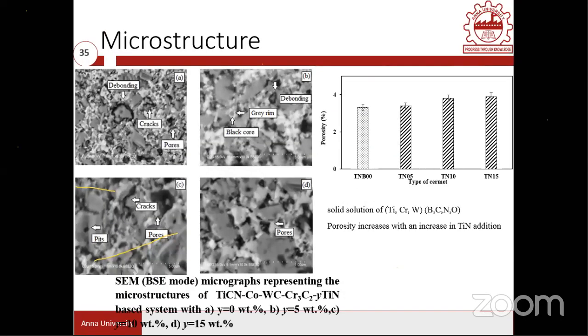This is a microstructure of a cermet after sintering, where one can see the gray rim structures and black core. There is a black core and also a gray rim, and you cannot distinguish the inner ring from the outer ring, but it's one ring. If you go to higher magnification, probably you can see the inner ring as well as the outer ring. As of now, you can see only the gray rim, which is comprised of both.